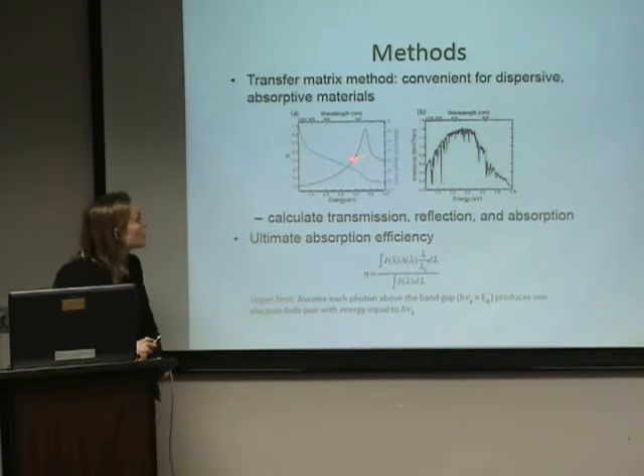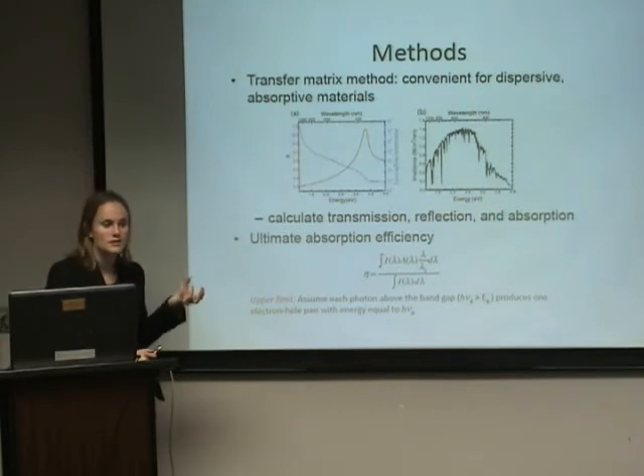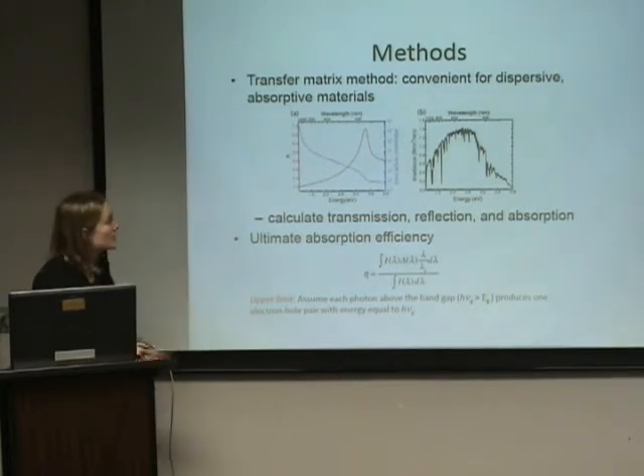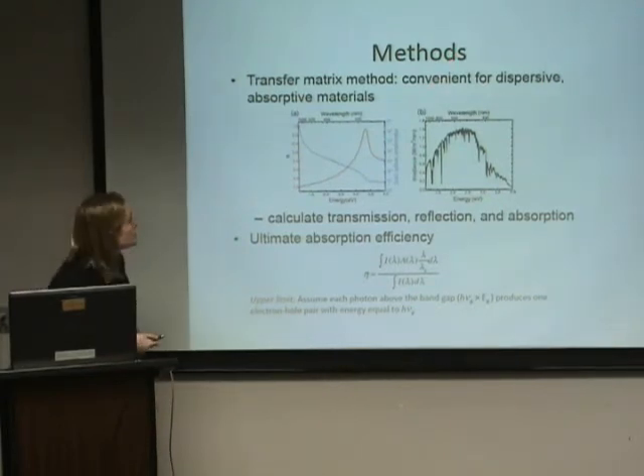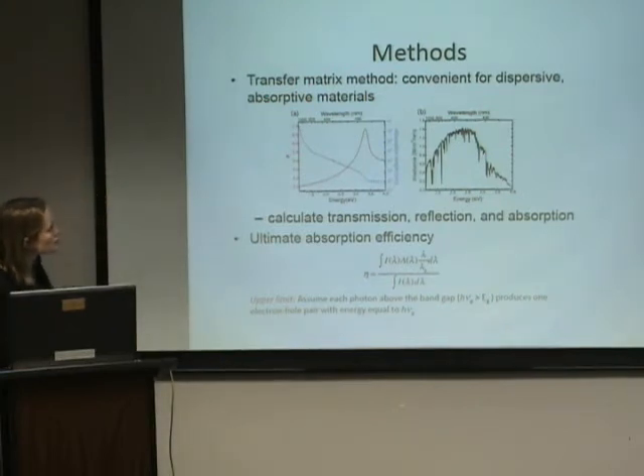So here, I mentioned a number of different methods that we use. For this particular problem, the transfer matrix method is convenient because if you're modeling the response of silicon across the entire solar spectrum, it's a very wide frequency range. The properties in the material change a lot. We call that, so in particular, the dielectric constant's dispersive. It changes with frequency. And this is also a good method when you have absorptive materials. So shown here, this is just the refractive index of silicon across the relevant range for the solar spectrum. We're looking at the range from 300 to 1,000 nanometers, or an energy that's something like 1.5 to 4 eV.